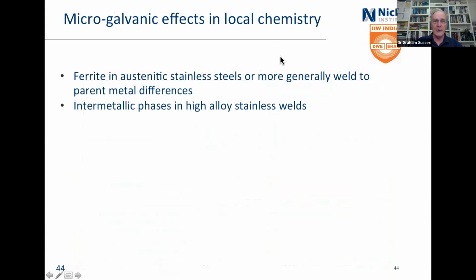So what about micro galvanic effects in local chemistry? This is ferrite and austenites. Yes, if the material is in an aggressive environment, then you can well get ferrite dissolving. There is a slight potential difference between them. It's not commonly a problem. And hey, you know why it's not a problem? And how I know it, because people use duplex stainless steels all the time, and there is very rarely problems